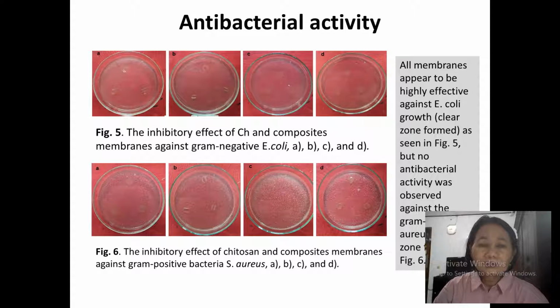Plus, we also conducted the antibacterial activity test, and we got that all membranes appear to be highly effective against E. coli growth. So there's a clear zone formed, as seen in figure 5, but no antibacterial activity was observed against S. aureus bacteria. We did not see a clear zone form.